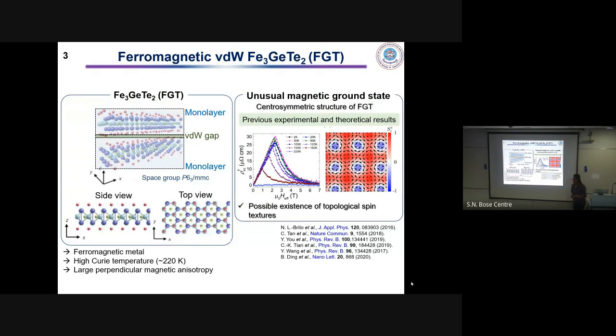So the question, perpendicular magnetic anisotropy, what does it mean? Perpendicular is specific, it's the out of plane direction, but anisotropy is with respect to in plane and out of plane. How can you define that it's perpendicular? I'll show it. This is perpendicular anisotropy when you compare between two orientations. Yes, and the magnetization value is quite large when the magnetic field is applied in the out of plane direction, and that is what I'm telling. Okay, it's a perpendicular magnetic anisotropy.